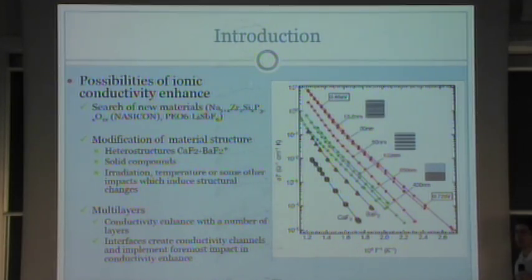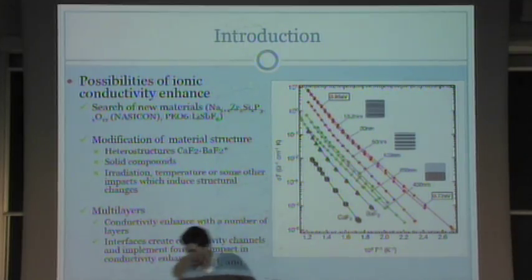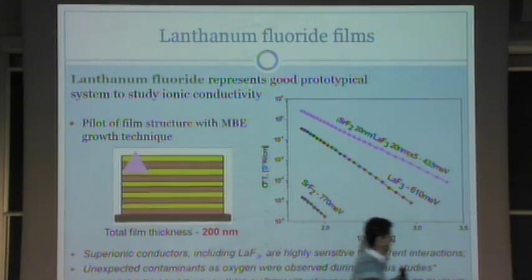So if we create a sort of heterostructure, multi-layer, or solid compound, you mix different solid electrolytes together, or induce several defects with temperature or some radiation. You can create, as you can see on the right part, enhancement of conductivity. Here is presented a multi-layer of calcium fluoride, barium fluoride, and as you can see, with increase of the number of layers, there are several orders of magnitude enhancement of ionic conductivity, which is actually good, and we've made sort of the same experiment, but with different fluorides.